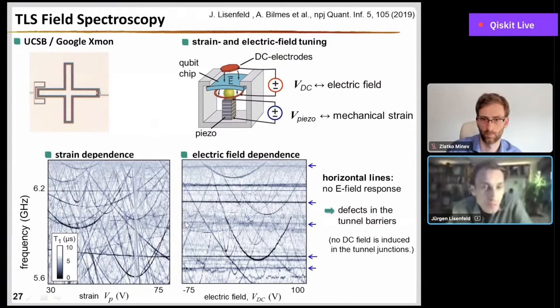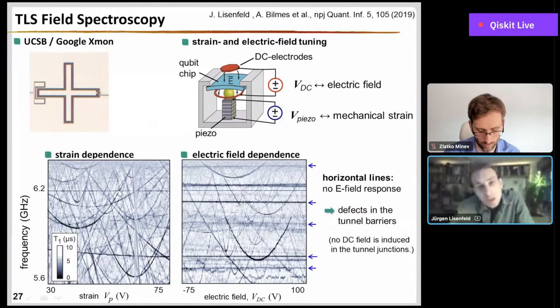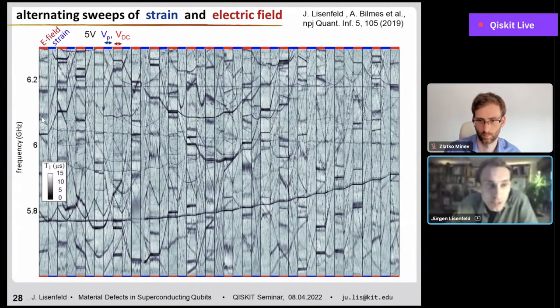We can, in principle, study the coupling of each defect to strain and electric field simply by following the resonance and tuning either the field or the strain. And this is how such a measurement can look. So we basically recorded here the TLS traces or resonances and varied first the electric field by increasing the voltage a little bit up to 5 volts here. Then we just varied the mechanical strain, and the field again, and the strain again.